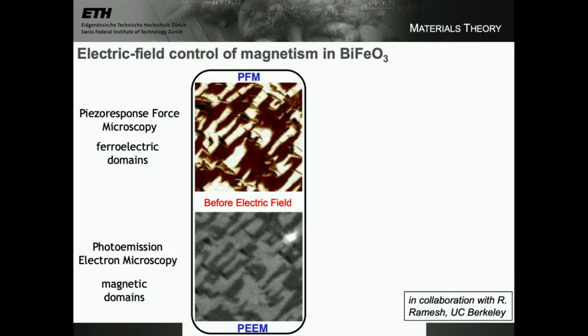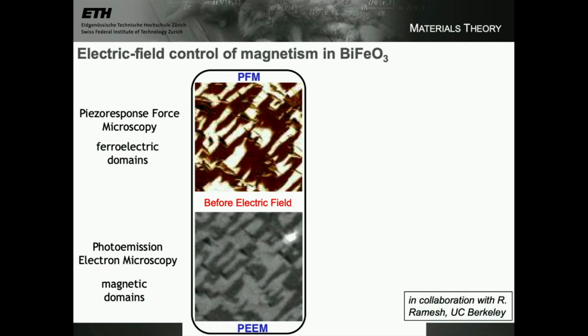In the bottom image, it's again the same region, but imaged using a technique called photoemission electron microscopy, PEEM, and this is sensitive to the magnetic domains. So in this case, the black and the gray correspond to magnetic domains pointing out of or into the screen. And what's the first thing that you notice about these two images? They're basically the same, right? So this is extremely encouraging, that there's some correspondence. If we look at this funny little shape here, this dagger shape, it's also down here. This triangle is up here, and so on. So before we do anything, we see that there's some kind of correspondence between the electric and the magnetic domains, which of course is important if we want them to be talking to each other.